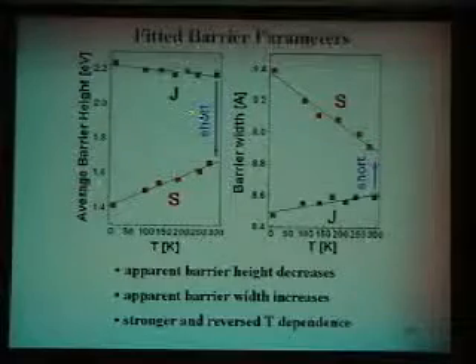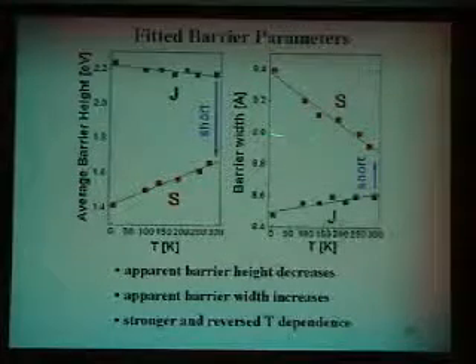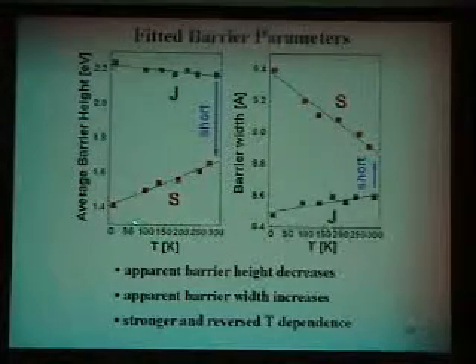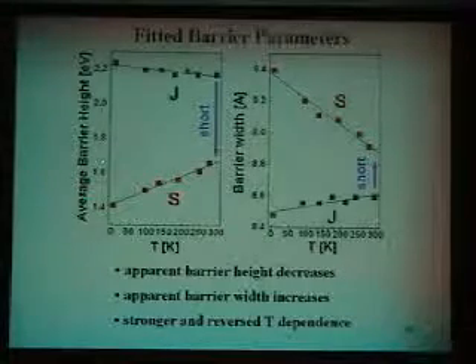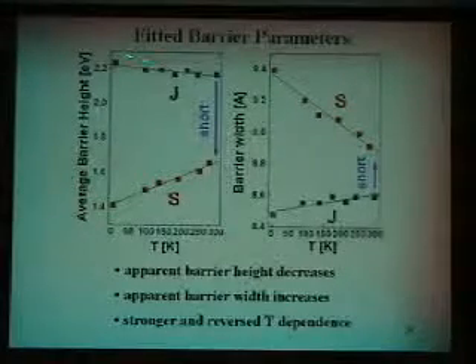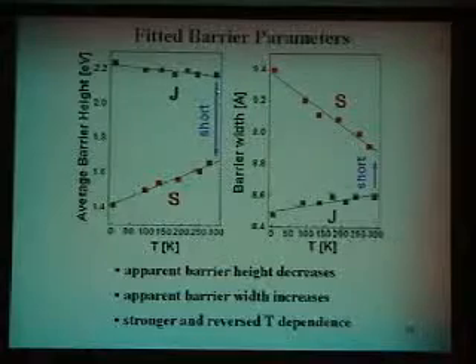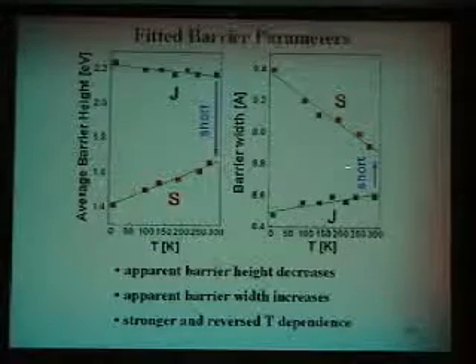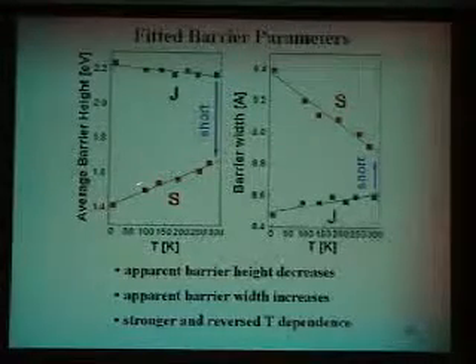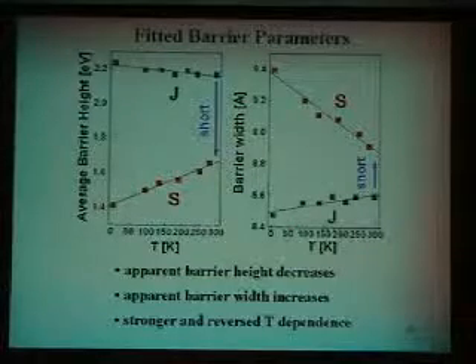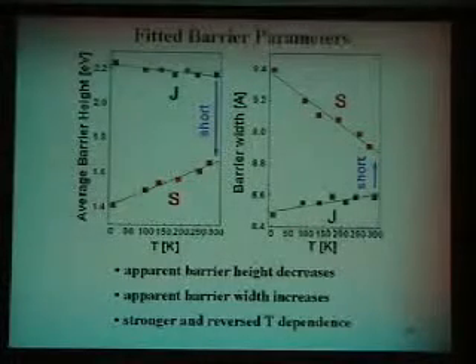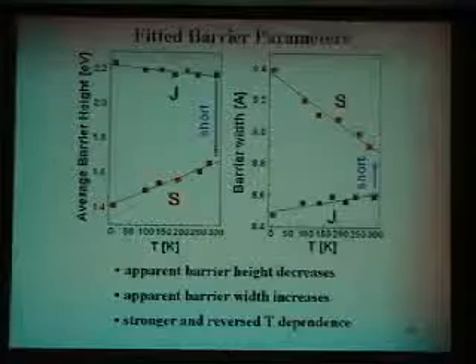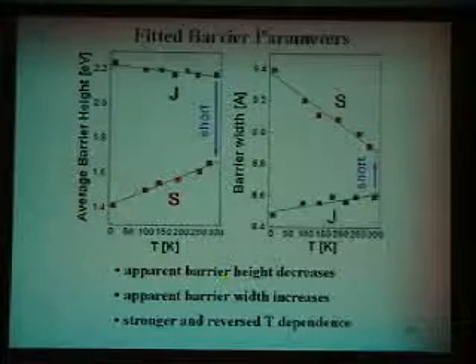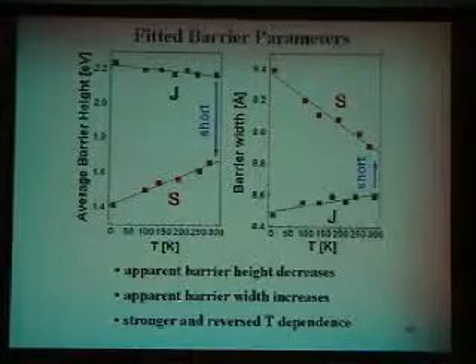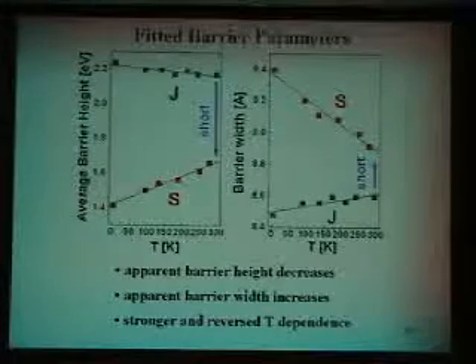Okay, so you can go through this exercise to fit the barrier heights, and this is what happens. If you fit the average barrier height, it changes with temperature in this way. The barrier width also changes that way. On the other hand, the short does the opposite. Okay, so when you zap it, things switch around and they do the opposite of each other. So what happens? The apparent barrier height decreases and the apparent barrier width increases.